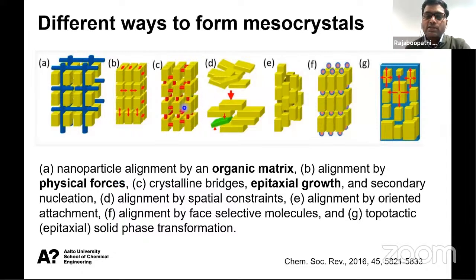This is a kind of epitaxial growth to produce mesocrystals. Here they used epitaxial growth, which means a kind of secondary nucleation. After forming the crystals, at the expense of the mother crystal, it will produce other crystals. We call it secondary nucleation or epitaxial growth. Here they use some external constraint to produce mesocrystals. This is oriented attachment. They use some face selective molecule to produce mesocrystals, and this is topotactic or solid phase transformations. So in different ways, we can produce mesocrystals.